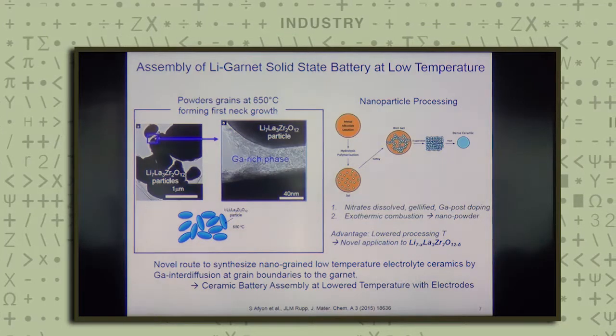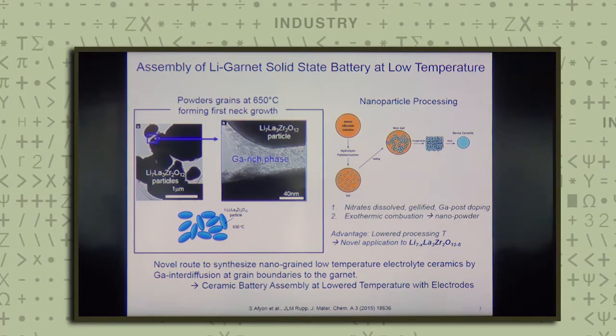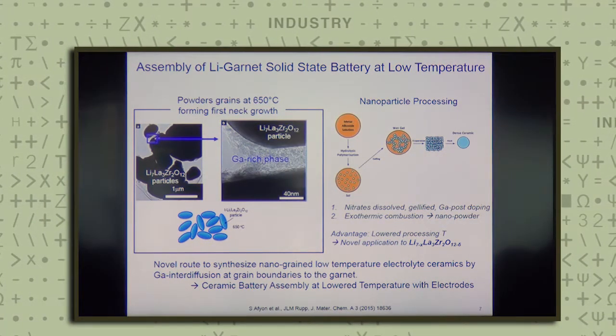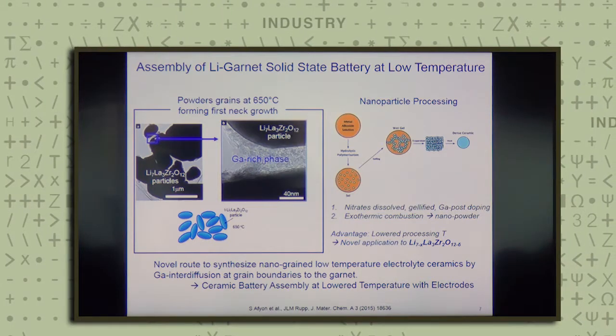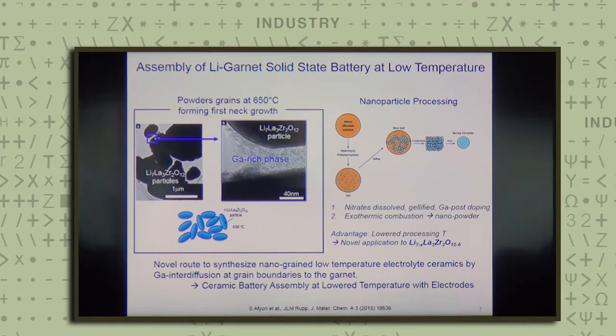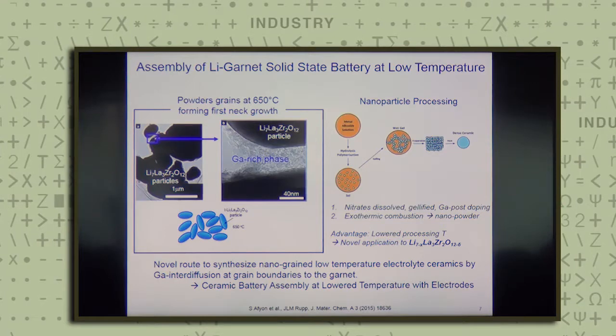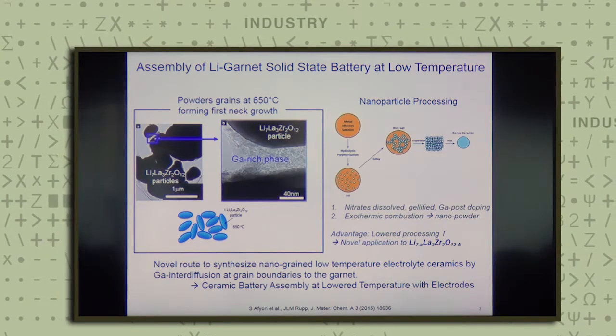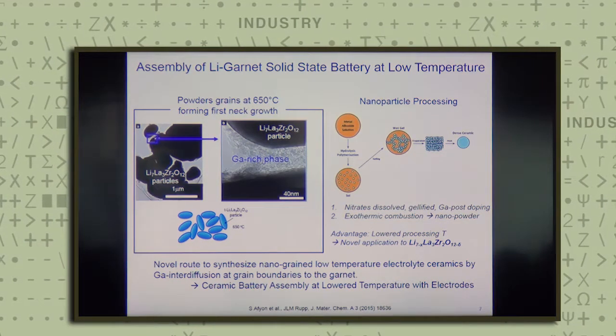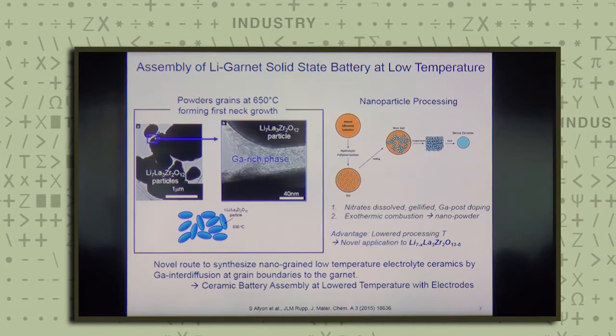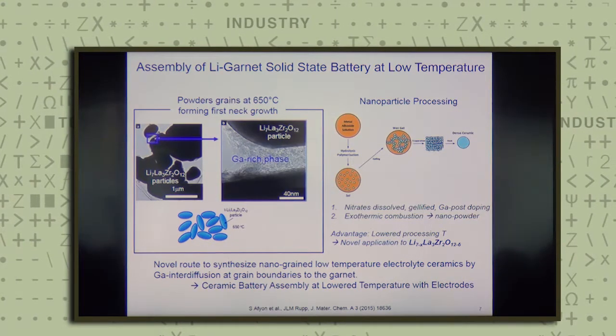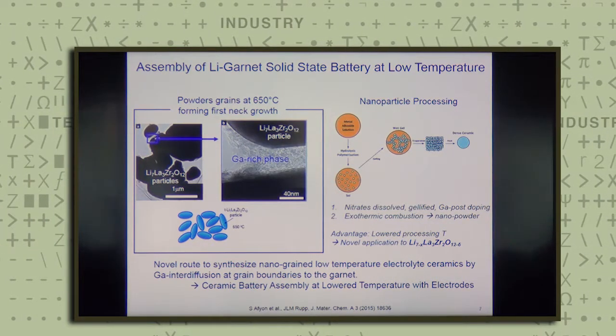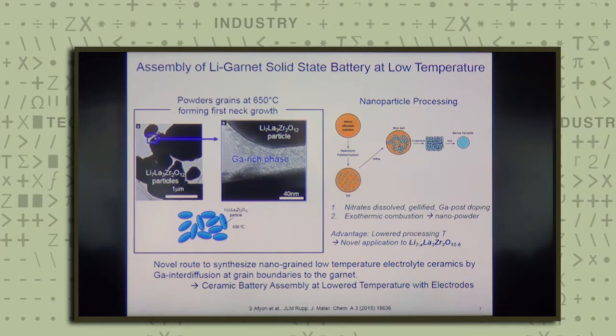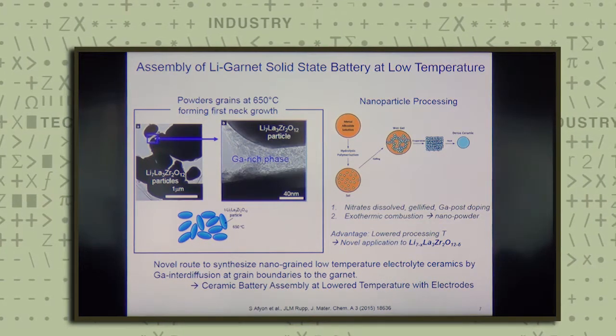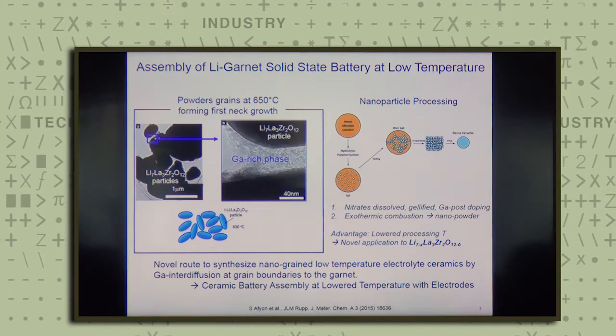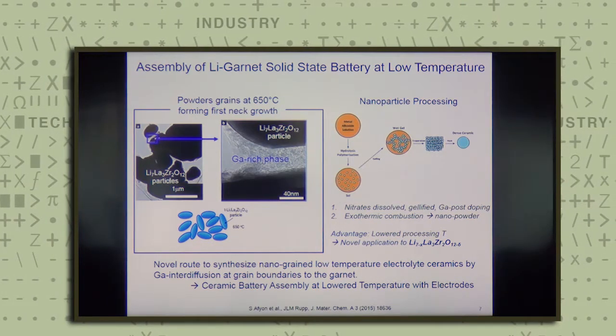So what we have done in my group is, first of all, to make some lithium garnet particles and to use a process where we coat these particles after we have made them in a nitrate sol process, for instance, with gallium and other elements that we use as a diffusing counterpart to go into the structure in an annealing process, and thereby stabilize these lithium garnet structures at an annealing and sintering temperature about 200 to 300 degrees Celsius lower than conventionally used in their processing.